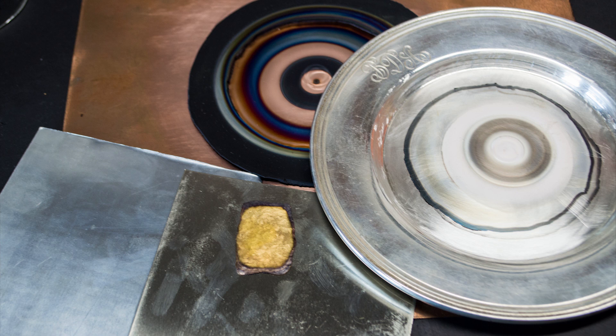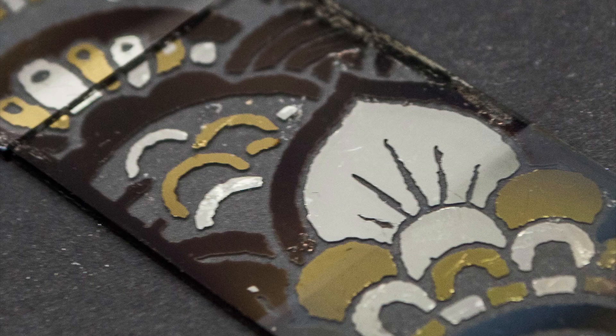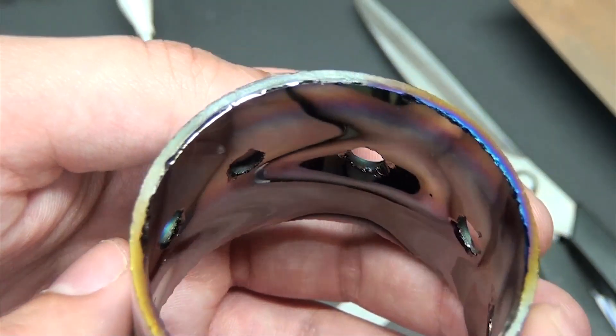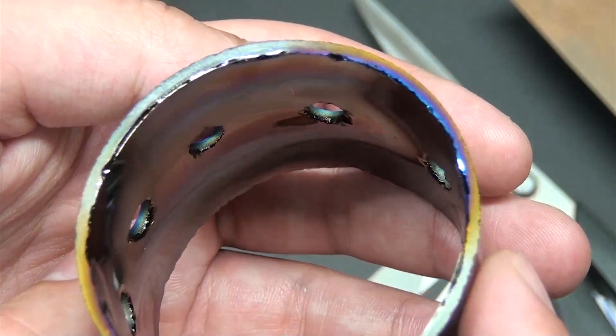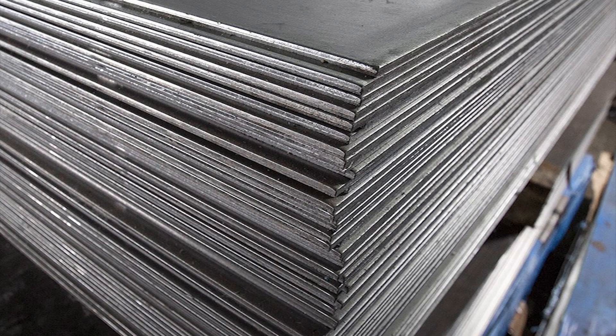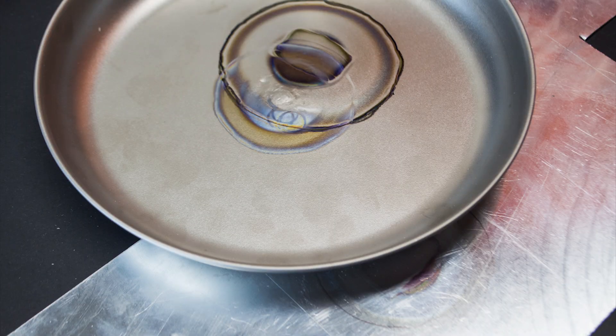With a few exceptions, most metals work with minimal effort and thus far I've successfully used the noble metals and nickel and they all work well. But keep in mind that ferrous metals like iron or steel need to be thinner as they dampen the magnetic field that makes this work. I'm sure many of you are wondering about things like titanium and aluminum and I figured out why they weren't working.